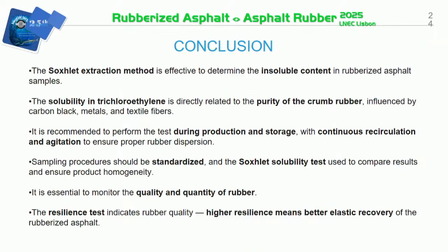In conclusion, the Soxhlet extraction method is effective to determine the insoluble content in rubberized asphalt samples. The solubility in trichloroethylene is directly related to the purity of the crumb rubber, influenced by carbon black, metals, and textile fibers. It is recommended to perform this test during production and storage, with continuous recirculation and agitation to ensure proper rubber dispersion.